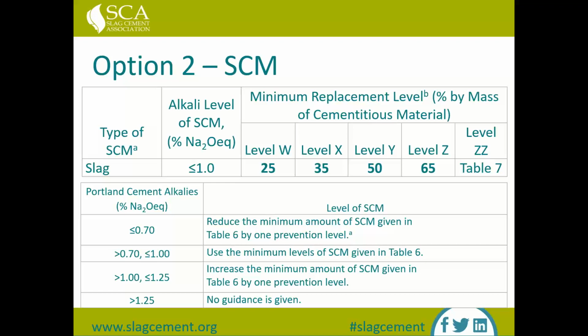Now you alter that top chart by that bottom chart, depending on the alkali content of your Portland cement. For example, if you're using a Portland cement with an alkali content of 0.55%, you reduce the level by 1 prevention level, so you move 1 column to the left. So if you need to mitigate to level X and you're using that 0.55% alkali Portland cement, you now move one column to the left, so you only need to use 25% slag replacement level in your mix.